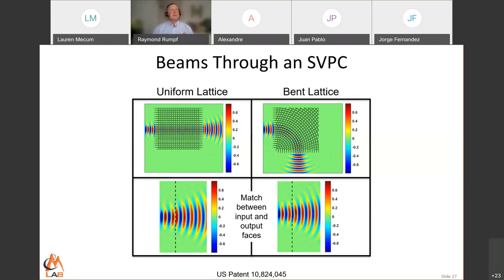Here's another reason this is really strange and what we can't quite explain. The beam traveling around the inside of a bend travels a shorter distance than the beam around the outside. One would expect the beam on the outside to accumulate more phase, creating a phase gradient across the output and causing the beam to go off at an angle. But it doesn't do that. No matter how many bends we have, the beam always exits similar to how it looked going in. We can't quite explain that, but it's an interesting observation.